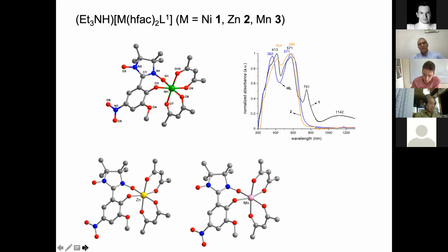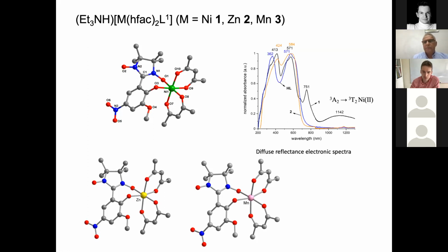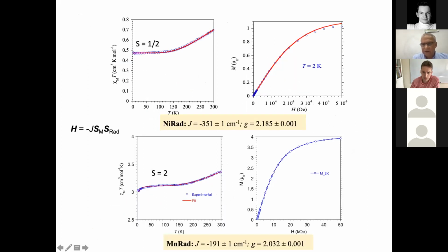First of all, in some cases, it is interesting to record the UV-visible spectra just for a better characterization, like in the case of the nickel complex here, because generally the strong absorption bands of the radical obscure the d-d transitions. But in some cases, like this one, we can observe the signature of an octahedral nickel ion. This is the first d-d transition of nickel(II).